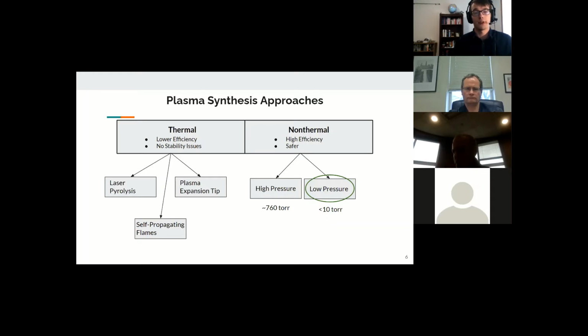One thermal plasma technique is laser pyrolysis, in which gaseous precursors, usually silane and acetylene, absorb laser radiation, which directly dissociates the precursor molecules, and a nucleation and growth chemical process proceeds within a flame. The flame has a temperature of above 1200 degrees Celsius, and the species in the plasma are all at a similar temperature, making it a thermal plasma. The self-propagating flame technique is similar to the laser pyrolysis technique, except it doesn't use a laser, and instead the flame propagates through an exothermic reaction.